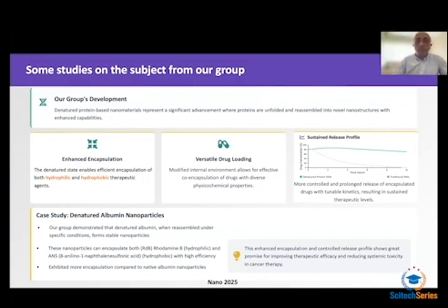millivolts, and after treatment with exosomes, and as you know, exosome is negative, the zeta potential of these nanoparticles decreased to approximately minus 7 millivolts. This confirmed that our dipeptide-based nanomaterials interacted with exosomes.